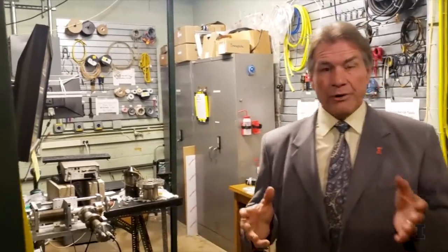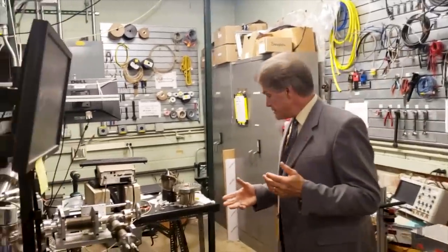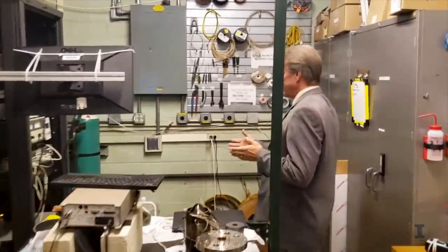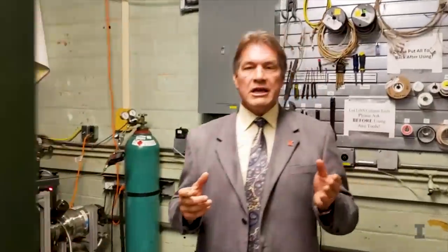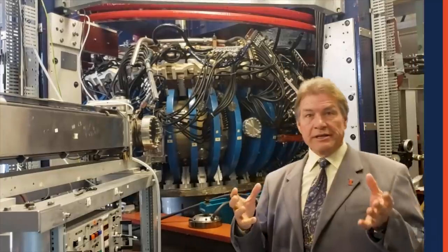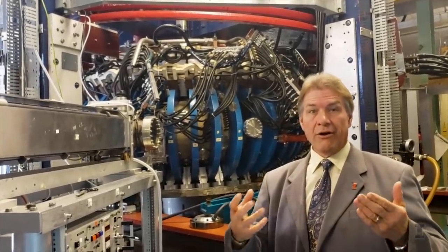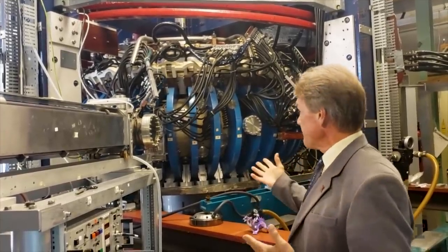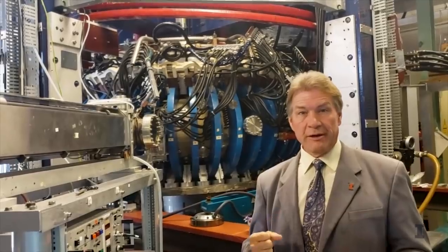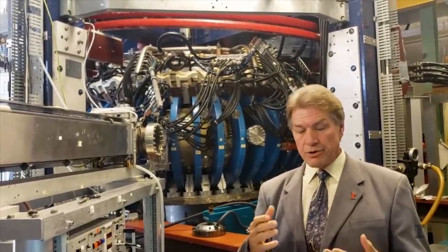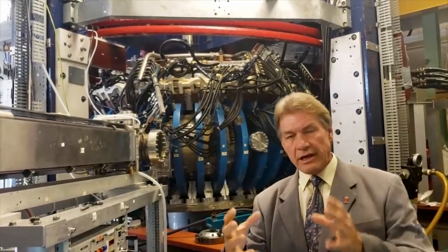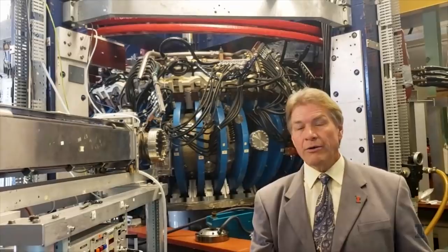In this part of my lab, we worry about taking the hydrogen and deuterium back out of the lithium. We have a number of devices to do this, all the way back here to our distillation column, which will show us if you can remove the deuterium fast enough to be able to make this whole system work. We need to test this in an actual fusion device that's under our control, and that's what we have HIDRA for, the Hybrid Illinois Device for Research and Applications, accelerator and a tokamak, where we will show that we can put lithium into the device, suck up the deuterium, pull it out, take the deuterium out, and do it all in a continuous loop. Now you might say, well, Professor Ruzic, won't the lithium get saturated?